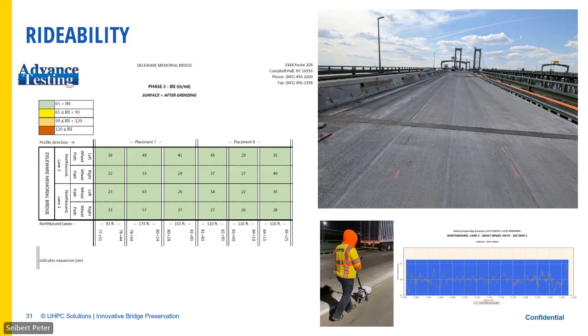Now, again, this is at a 4% longitudinal slope and 2% cross slope with traffic moving on the same structure, just adjacent to us. So definitely challenging. Well, we found that from phase 1 to 2 to 3, we made improvements all the way through. And our best rideability came when we overfilled by 3/8 of an inch, a little bit more than the typical recommendation. And we did the grinding in 2 passes.